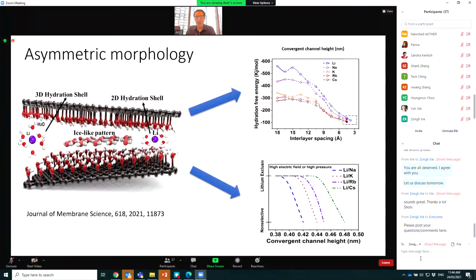So what we found is that we tried to create that sort of morphology to push this ice-like pattern at the very end of the nanochannel and keep the entrance open enough for the ions to move through the nanochannel. Using that, we've observed a very interesting phenomenon. A membrane without any lithium selectivity became lithium exclusive, only allowed lithium,